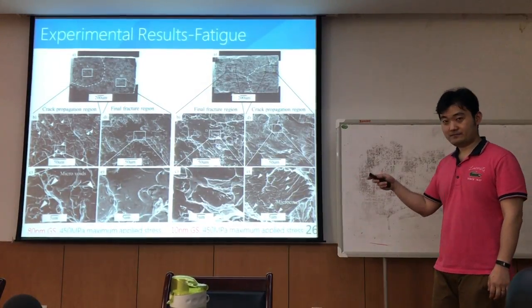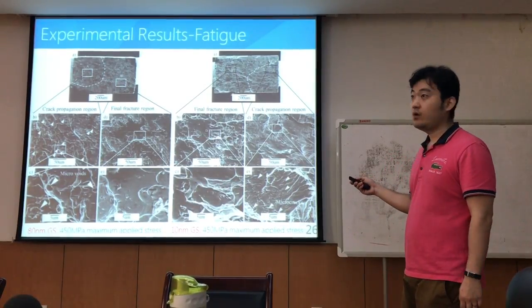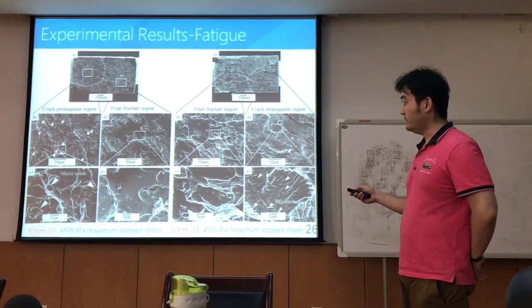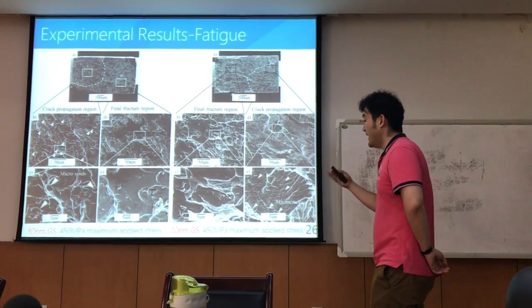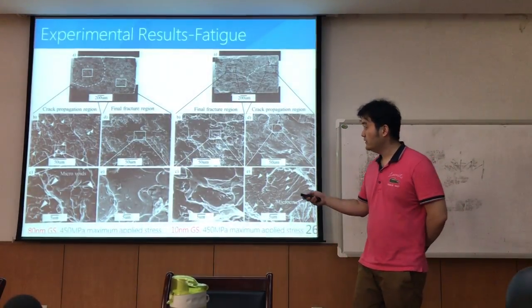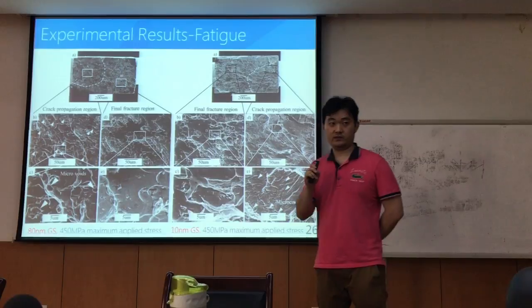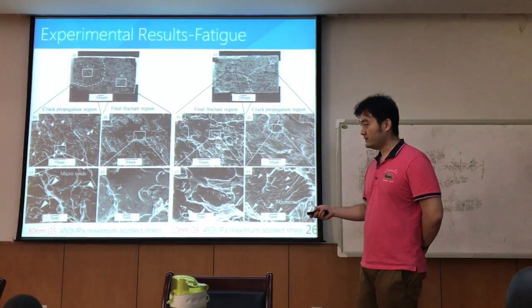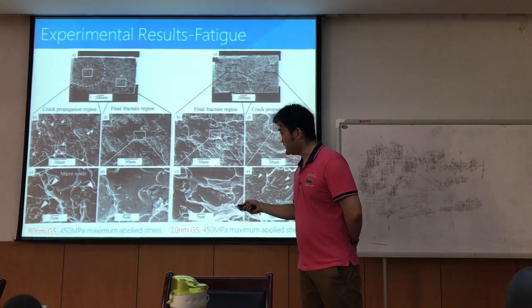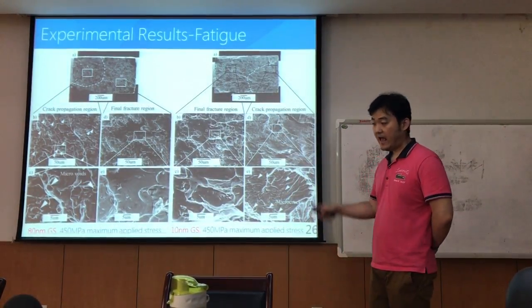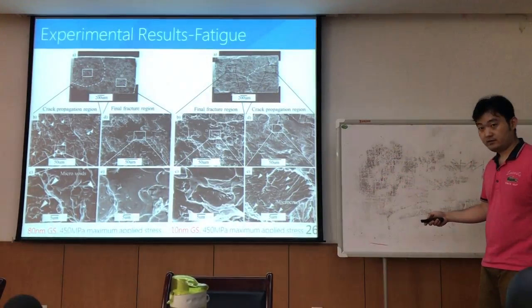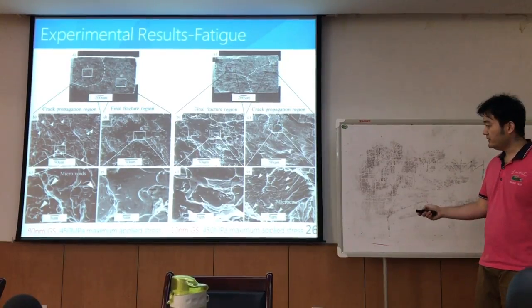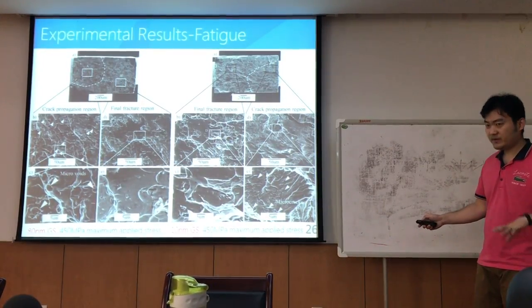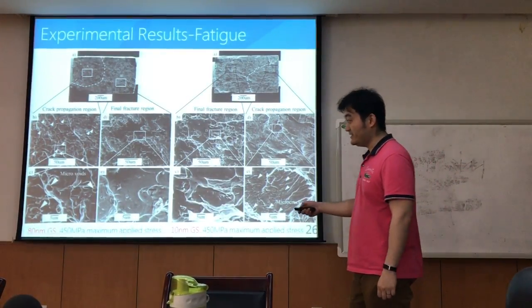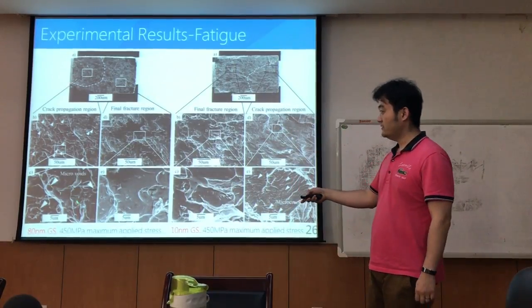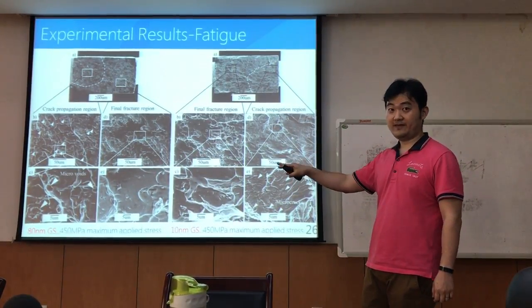Okay. So again, for the fatigue life, why are they different? We observe the final fracture surface by SEM. We find that for the crack propagation region, they have different morphologies. Okay? For the large grain size specimen, we see some micro voids. However, for the small grain size specimen, we can only see some micro features. This is a typical metal fracture surface morphology, but this is not. Okay, but we can find some similar morphologies for dual phase steel.